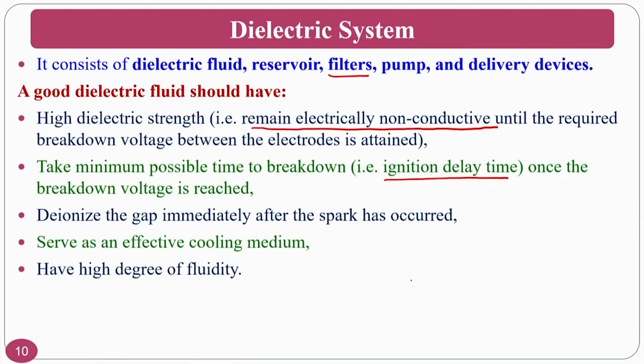At the same time, with this cooling, the molten metal will be carried away in the form of spheroids and other things. That is why, whenever you see the surface morphology of an EDM surface, you can see some of the spheroids on the recast layers. This recast layer, heat affected zone and other things we will come across in the upcoming slides have a high degree of fluidity. That means the viscosity should be low.